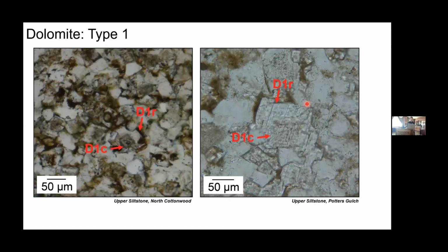And just to give you an idea of what this looks like in thin sections, since most of us look at thin sections, here again you can see the cloudy nature of this dolomite core with a much clearer rim, making these pretty easy to recognize in thin section. And then here's the view of when the crystal is a little bit bigger and zoomed in a little bit further. You can see the cloudy nature of the core relative to the rims that we saw in the EDS.